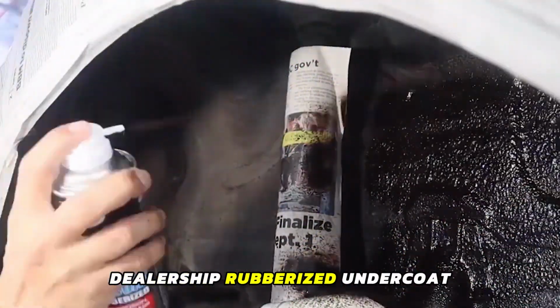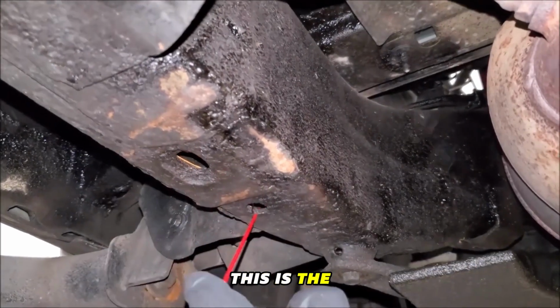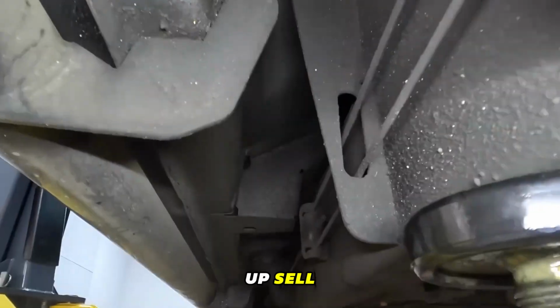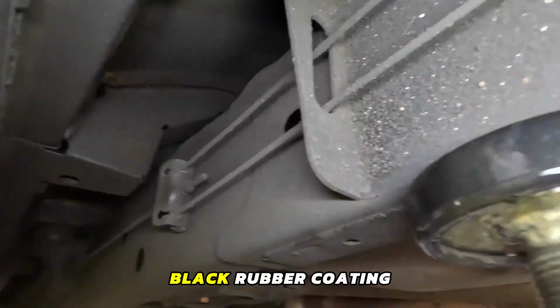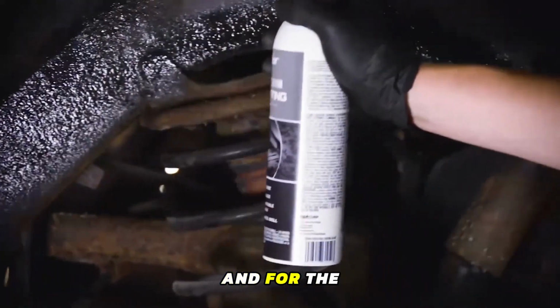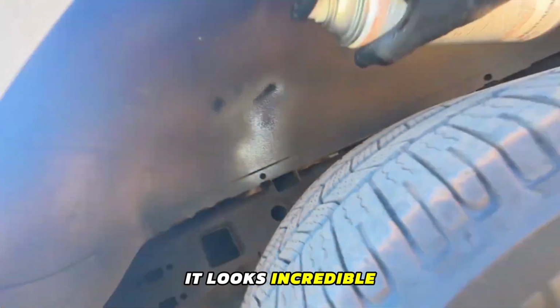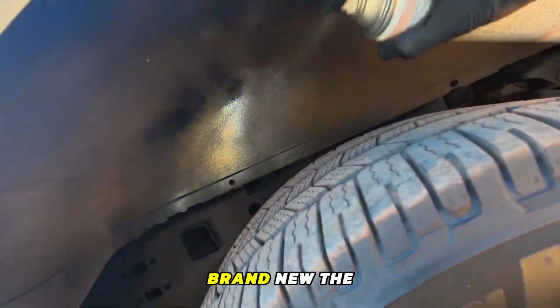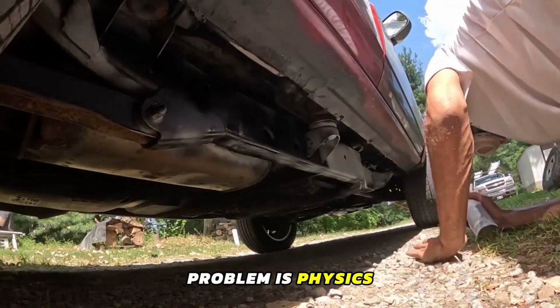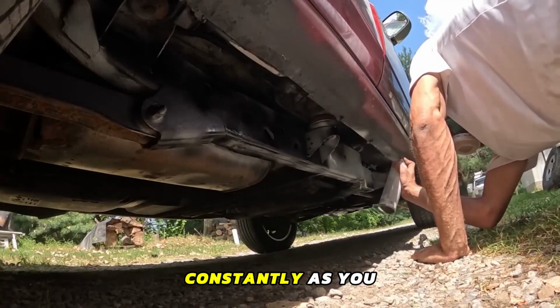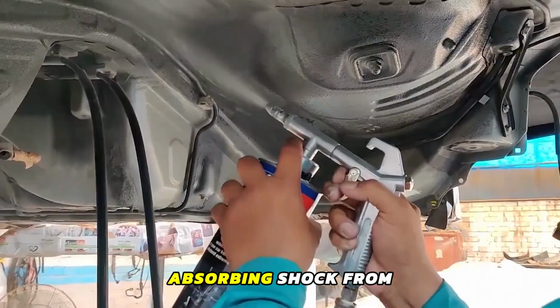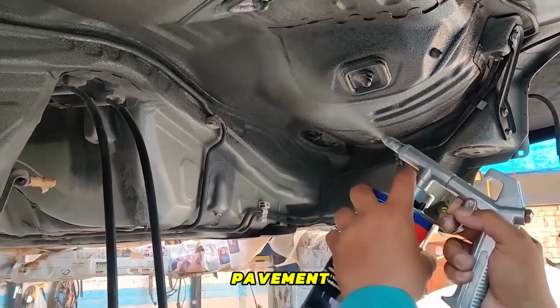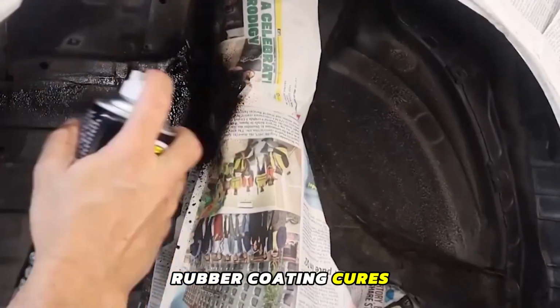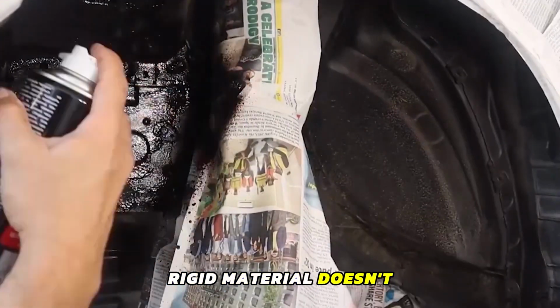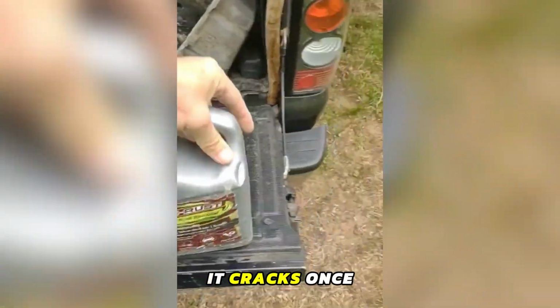The dealership rubberized undercoat. This is the classic finance office upsell. A technician sprays a thick black rubber coating across your frame, and for the first few months it looks incredible. Uniform, glossy, brand new. The problem is physics. Steel frames flex constantly as you drive, absorbing shock from potholes and uneven pavement. Rubber coating cures rigid. Rigid material doesn't flex with moving steel, it cracks.